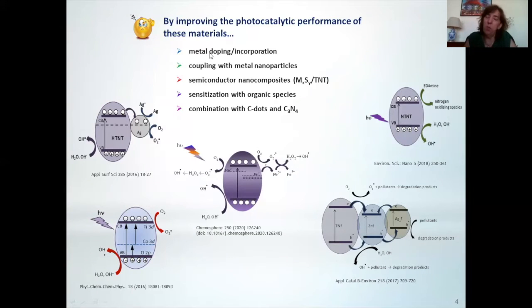We have tried, for instance, to modify these particles with metal by doping or by incorporation. I will show you in a few minutes the difference for us between these two cases. We also have some works related with the combination of the titanates with some metal nanoparticles, preparation of some nanocomposite materials, and in this case, the layout of the final catalyst is very important. We also can try to synthesize this particle using, for instance, some organic species. And more recently, we are trying to combine them with carbon dots and carbon nitride nanostructures. These are only some examples of the work that we have been developing in the last years, but I would like to spend 2 minutes in this case.